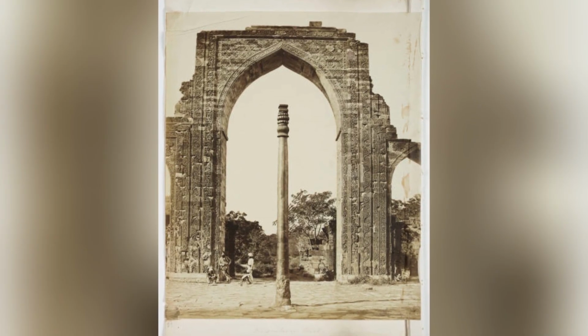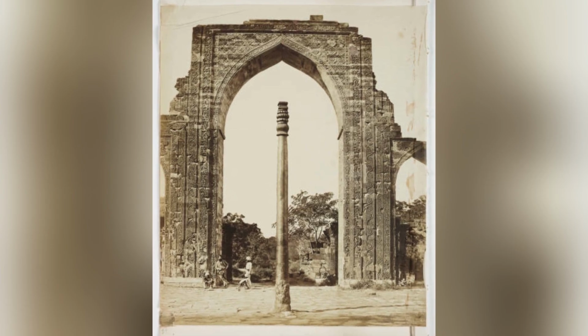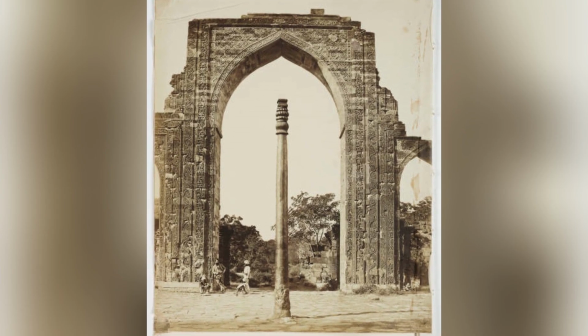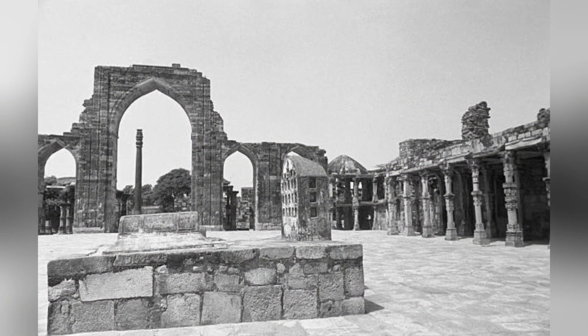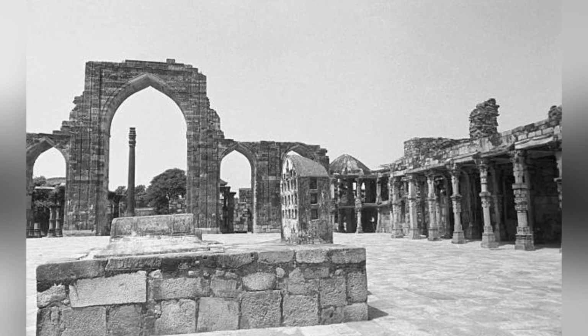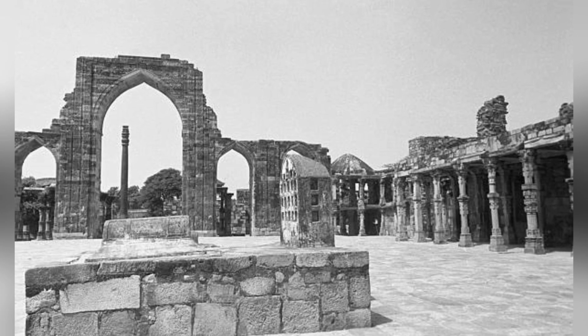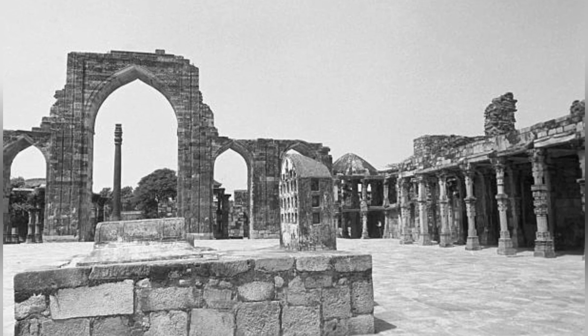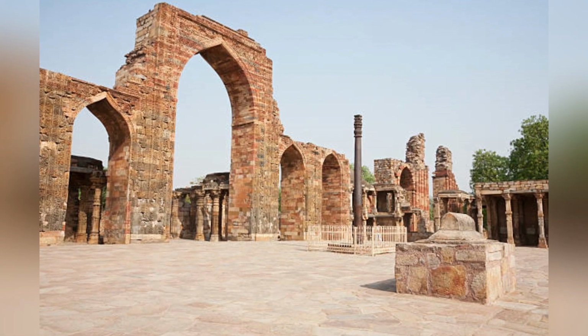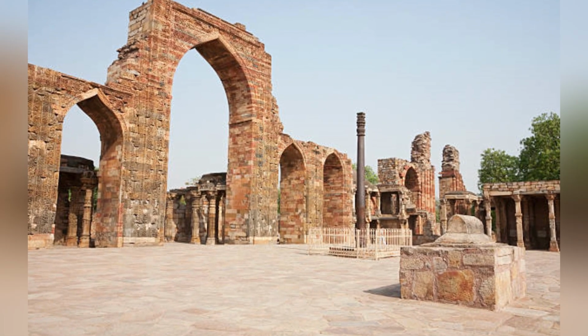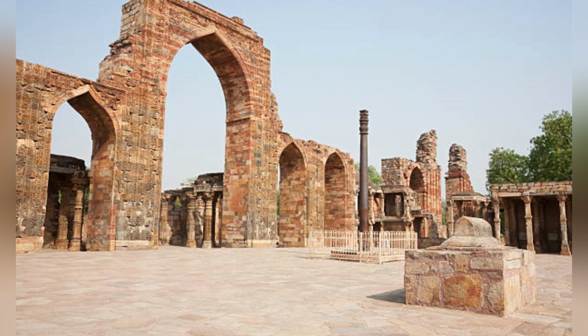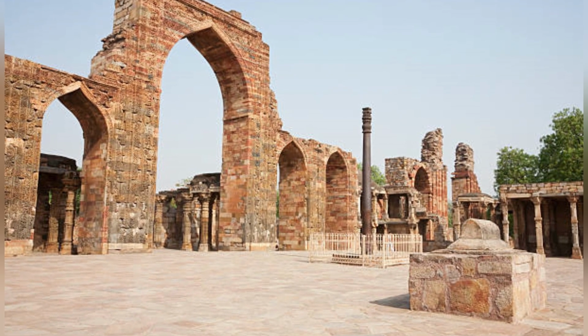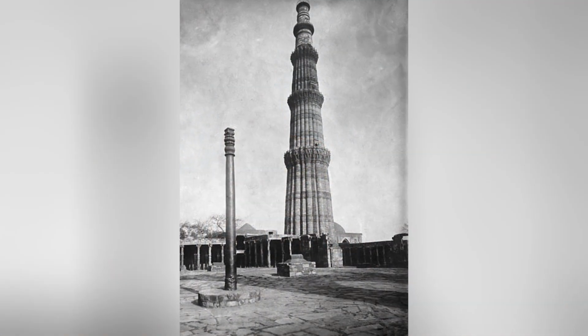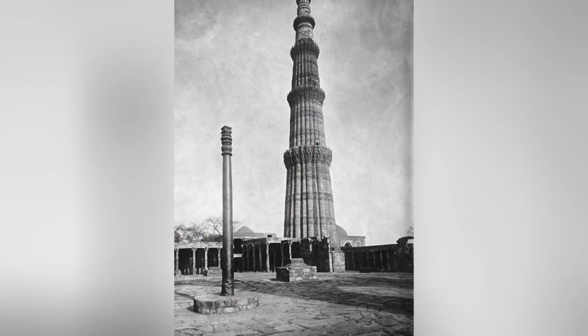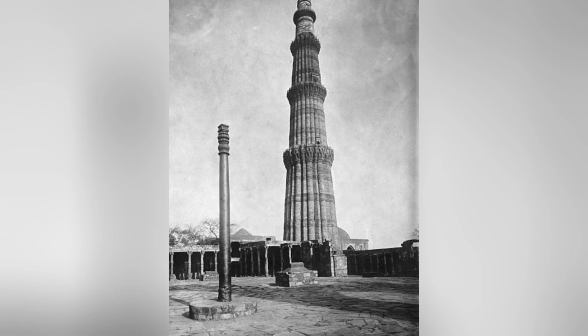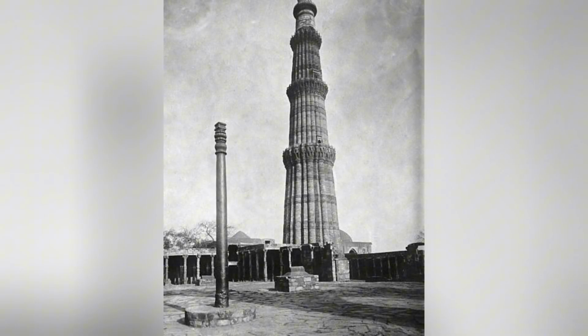The mathematical modeling of the film formation process, using equations that describe the rates of dissolution, precipitation, and diffusion of the phosphorus and iron species in the film, has been used to predict the long-term behavior of the film under different environmental conditions. The models, which have been validated by comparison with the measured properties of the film on the Delhi pillar, predict that the film will continue to grow and to improve for several more centuries before reaching its maximum thickness and its maximum protective capability.